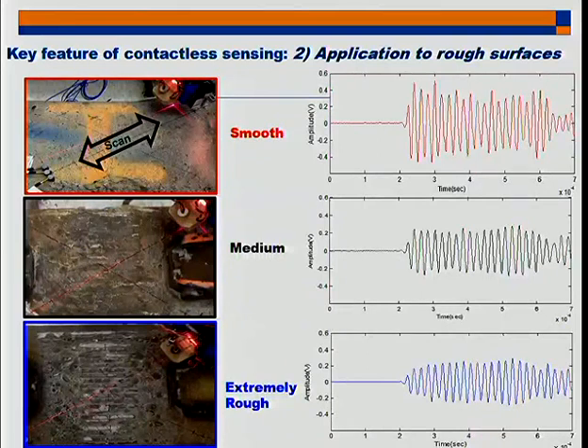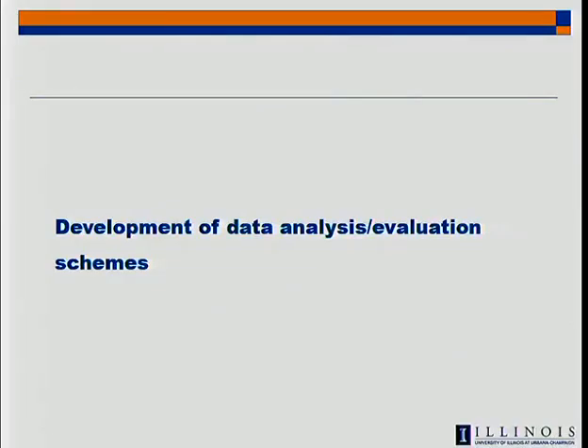But air-coupled sensors don't really care about the cleanliness of the surface or whether it's rough and undulating. We can still get energy in. So here we have three different surfaces. Here's an idealized, smooth, clean surface. Here's a moderately rough surface, and here's a very rough undulating surface. In this one, it would be very hard to mount an ultrasonic transducer or sensor on there without grinding down and getting good surface coupling. But we're able to get quality signals throughout because it's air coupled. So there are advantages. We don't have to pre-treat the material in any way, at least that we've seen yet. I'm sure there will be cases where it's just too crazy to even apply air coupled. But OK, so that was a little bit of intro.